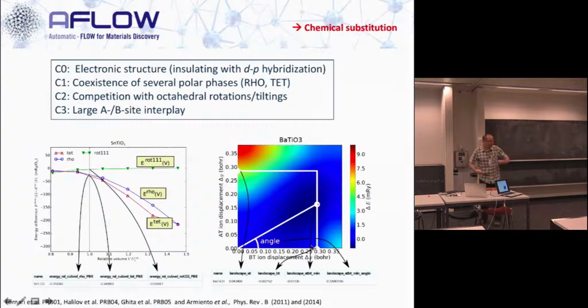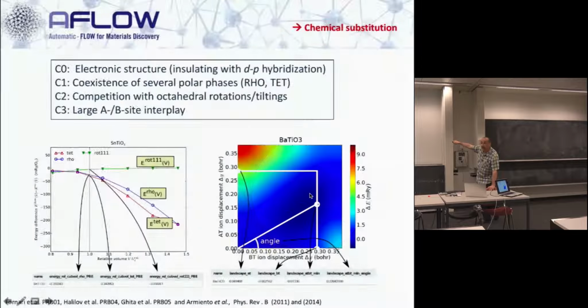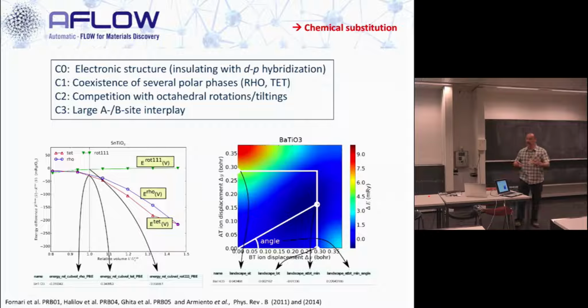So we took this, we computed all these graphs, and then we parameterized those to put them in the database. So here we are reporting the minimum along the tetragonal, for the A site, a minimum for the B site, the minimum in the phase across the global minimum on the map, and the angle at which the global minimum occurs. So if the angle, for instance, is close to 45, you have an idea that there is an interplay between the A and the B site. If the angle is close to 0 or 90, you have no such interplay.